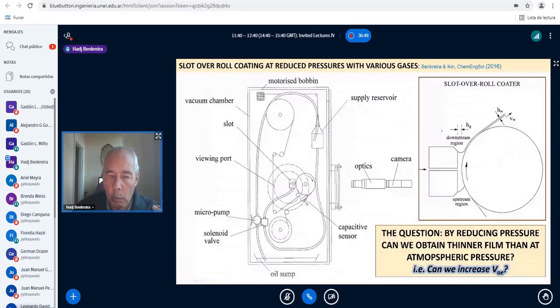Typically we obtain a 17% reduction. The reason being that in our very crude chamber, we could not go below 15-20 millibar. So if we could do experiments at much lower pressures than 25 millibar, we would go even lower.